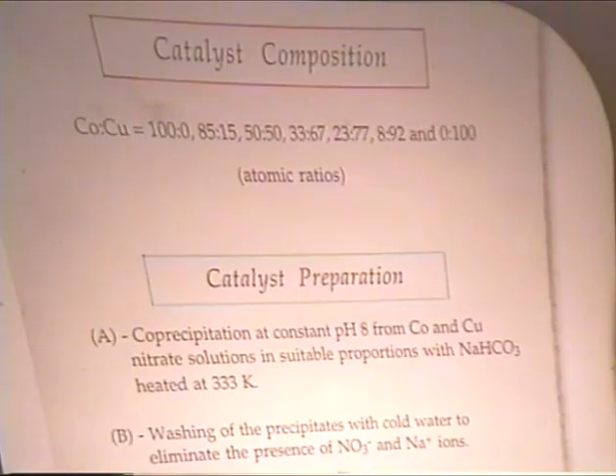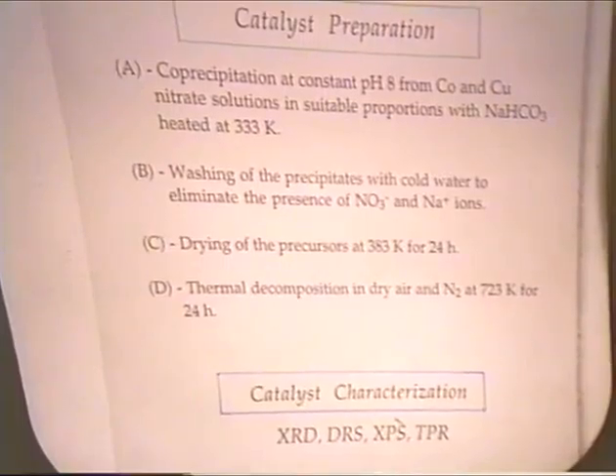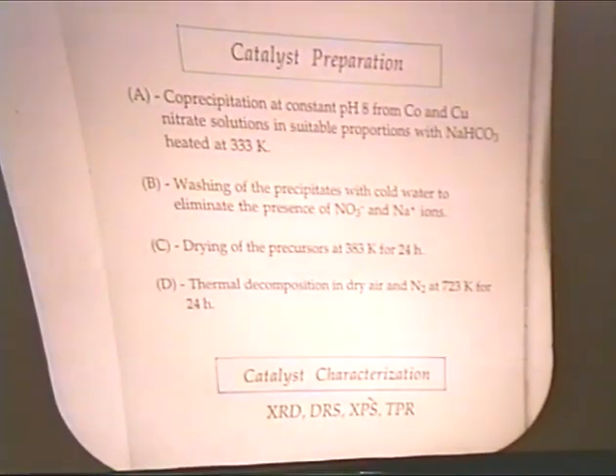And this is very important in order to obtain, upon decomposition, well dispersed mixed oxides in intimate contact with each other. The precursors were finally decomposed both in an inert atmosphere and in dry air at 723 K for 24 hours. Both the precursors and the final catalysts were characterized by several techniques: X-ray diffraction analysis, diffuse reflectance spectroscopy, X-ray photoelectron spectroscopy, and temperature programmed reduction.